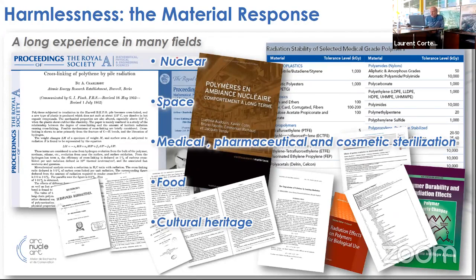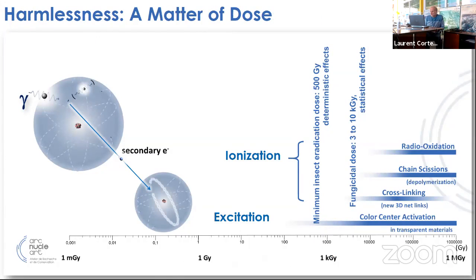So when you apply that kind of treatment to cultural heritage, one thing very important is the harmlessness. Behavior of material under irradiation has been largely studied for nuclear application, for space, for medical, for pharmaceutical and cosmetic sterilization, for food sanitization, and also for cultural heritage. We know that once again it's a matter of dosage. The first effect that can give us some problem with cultural heritage is the activation of color centers in transparent material. It can occur even before 1 kilogray at a slight level, but it can happen. So we must avoid transparent material.